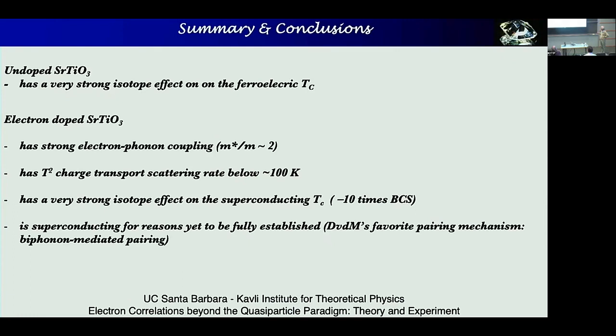And then there's a very strong isotope effect on the superconducting TC, which has the opposite sign as BCS theory, and it is at least 10 times bigger than BCS theory predicts. So that's confirmed by 3 different experimental groups. It's a real effect, and it was actually predicted, but somehow not an entirely correct model.